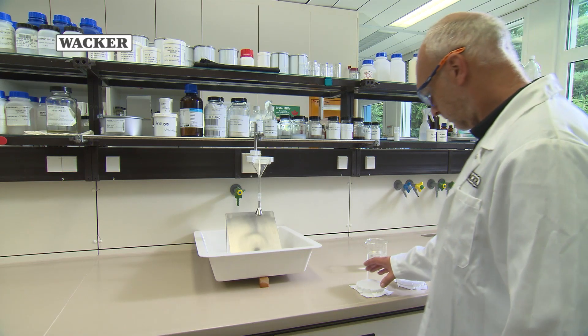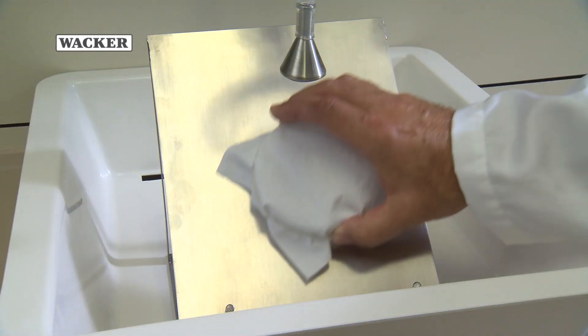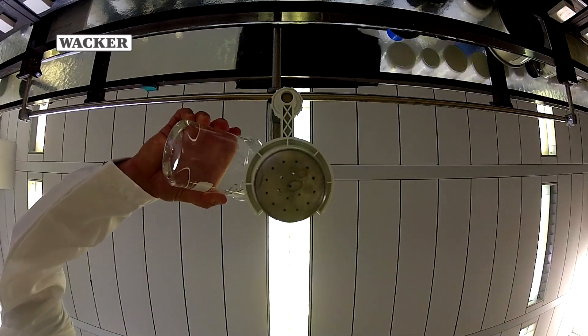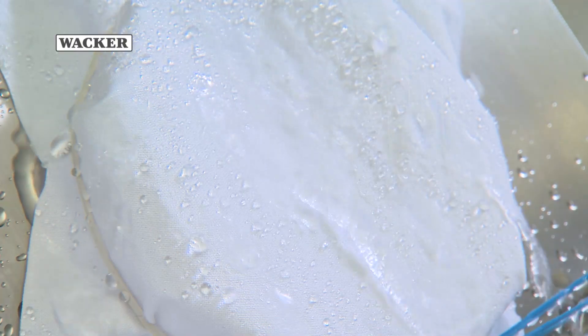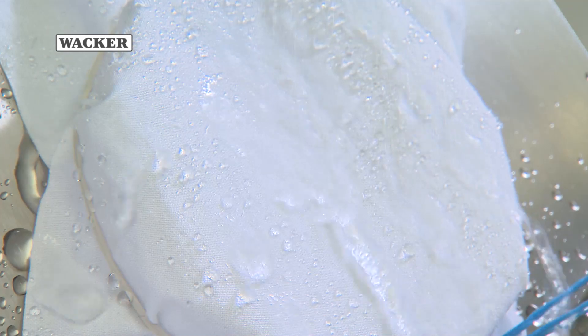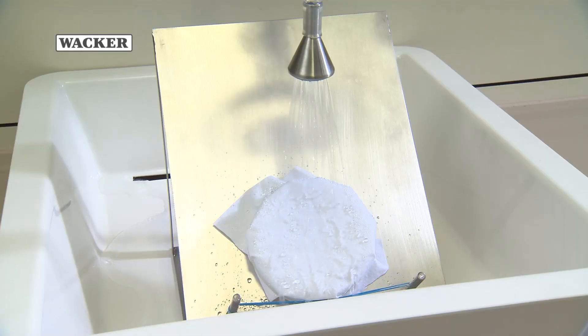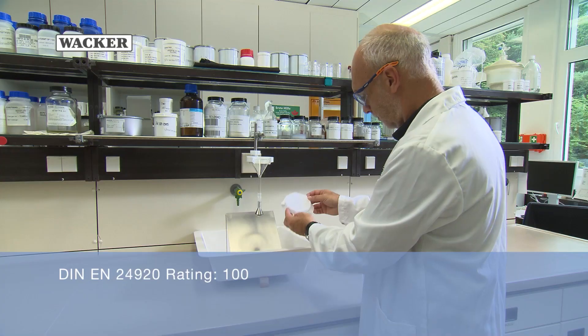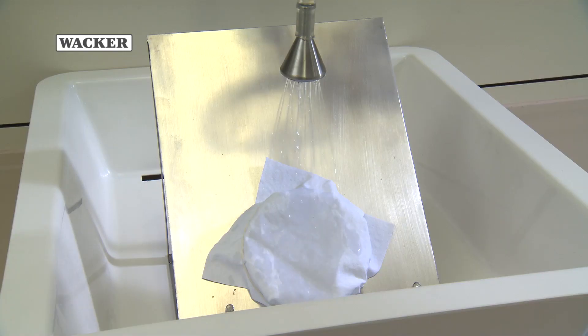The spray test shows the water-repellent surface with and without Leosil HC-603E. The spray test is rated on a scale of 0 to 100, according to DIN EN 24920. Following treatment, the fabric exhibits less wetting. The water beads and drips off the surface, and the fabric stays dry.